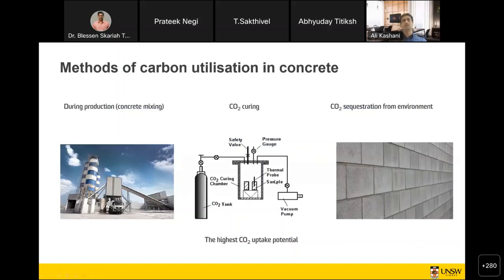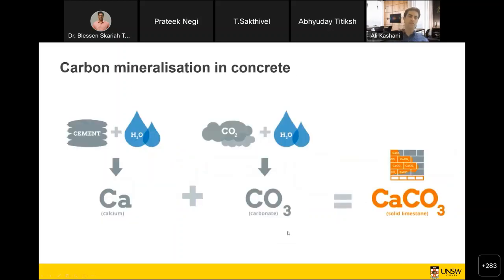There are different methods by which emitted CO2 can be captured and utilized in concrete. It can be during production, for example concrete mixing, where a liquid version of CO2 can be mixed with the material. And there is CO2 curing, especially for precast elements, where we can put them in a chamber and cure them with CO2. Also, CO2 sequestration can happen to any concrete structure during its lifetime. It's very slow. They call it recarbonation, but the extent of CO2 uptake in a short amount of time is pretty low. The high CO2 uptake happens in CO2 curing compared to the other methods. That's why we are working on that.